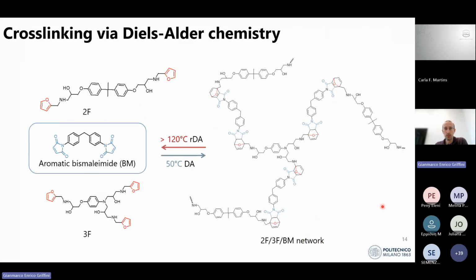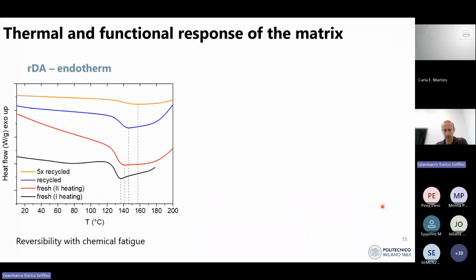Of course, the first point to look into is the reversibility of the system, which means thermal reversibility. This was verified through differential scanning calorimetry, and you see here the reversibility is indicated by the presence of an endothermic peak at relatively moderate temperature. Let me also stress the fact that upon successive cooling and heating, there is a sort of chemical fatigue, due to the formation of irreversible bonds that lead to a reduction of the endothermicity, which is essentially intrinsic of these types of materials.